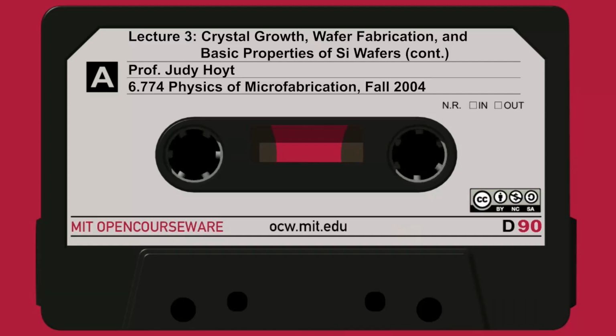Here's a picture of a piece of silicon, and this region up here in the upper right is doped very heavily with arsenic. So it has a donor concentration of 5 × 10^19 per cubic centimeter, and the rest of the crystal is boron or p-type doped very lightly at 10^15. And we take this PN junction and we heat it up to 1,000 degrees in a furnace. And the question is, let's sit down and calculate, using the Shockley equations, the concentration of all the different charge states of vacancies and all the different charge states of interstitials. And let's just see in those two different regions what the concentration of these point defects is, here and here.